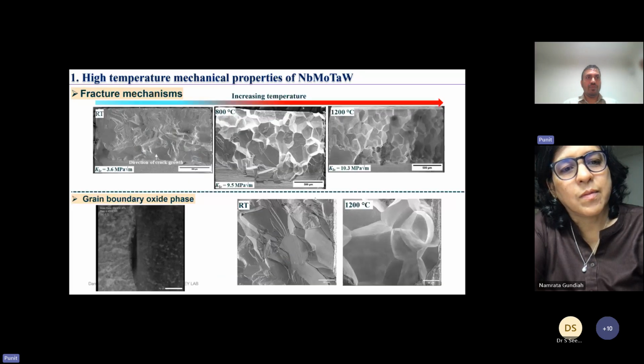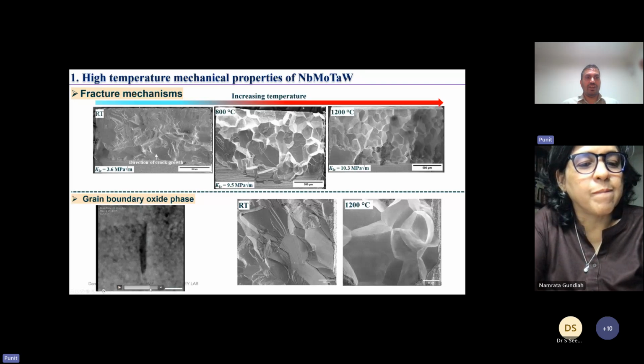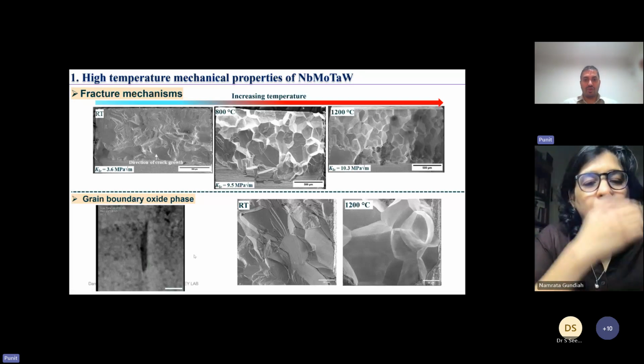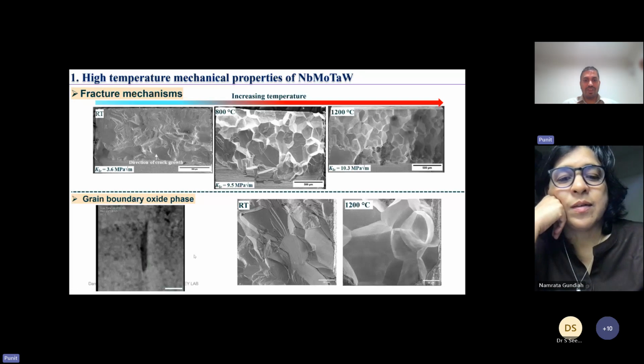In the TEM experiment, we see that these oxide particles actually dissolve around 900 degrees C. So what we did is we took some of this material and heated it up to our test condition, about 1200 degrees C, and kept it there for the whole test period without applying any stress. We cooled it down and looked at the microstructure again, and we saw that there was not much change in the morphology or types of oxide on the grain boundary.